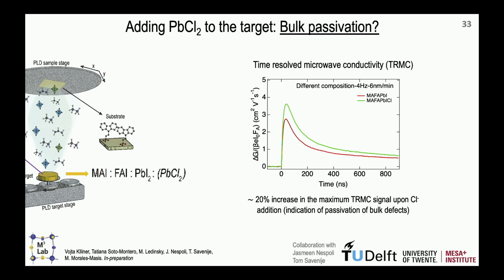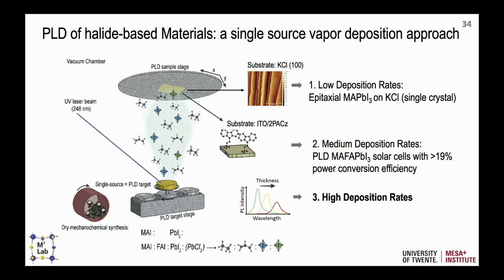Okay, and now I mentioned a little bit of passivation, bulk passivation. In that paper, we show everything in terms of devices. But now we are taking a step further, and this is our next collaboration to highlight here, with TU Delft, together with Jasmeen Nespoli, who is also here, and Tom Savenije, because now we can also do mobility measurements together with them. And what we notice very systematically is that if we add chloride in our films, the mobility actually increases. And we do it with other materials and other deposition rates. And we can see in this graph, using time-resolved microwave conductivity measurements, that adding chloride is really helping, probably to make the grain sizes larger and improve the mobility. And that's probably one of the reasons it is helping. So this is ongoing work, but also, again, an example of collaboration that we will benefit from, also part of the solar lab.